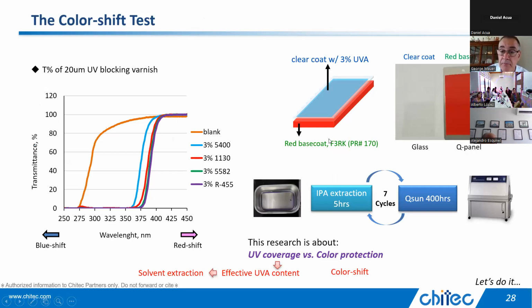Okay. So in this test, we did a red, and we picked the red on purpose because there's some automotive pigments that are a little bit more sensitive to color shift than others. You don't have to go out quite as far. And of course, some colors won't shift. Black is black and white is white. Those generally don't shift in color very much. And some of the blues are pretty stable as well. So we picked the red so that we could actually see the differences and see the impact of the UV absorber in a more pronounced way. So it's a tougher test.